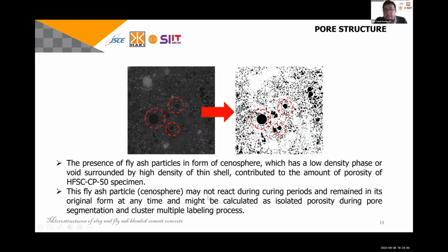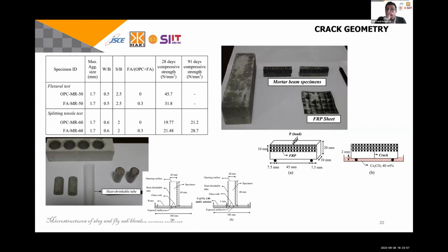And then this fly ash particle may not react during the curing period and remain in its original form at any time, and might be calculated as isolated porosity during the pore segmentation and cluster multiple labeling process. And then for the crack geometry, again here we prepare two types of specimen. One conventional, I mean OPC, and the second one using fly ash. Two types of crack: first, generated by flexural load, and the last one generated by splitting tensile load.